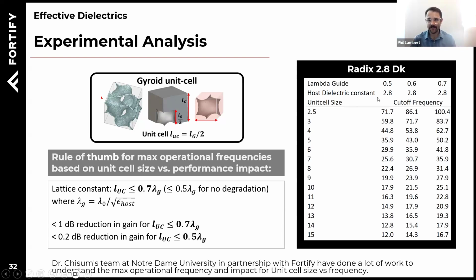So on this table here, if you look at your unit cell size, and so long as that unit cell size is 0.5 of your guided wavelength, then you will have an effective cutoff frequency in this column here. And so for the host dielectric of 2.8, which is a Radix 2.8, with a unit cell size of say 5 millimeters, you can follow this and see, okay, we expect this 5 millimeter unit cell to operate pretty perfectly up until about 35, 36 gigahertz. If we wanted to go lower frequency, we could tolerate a higher unit cell size.